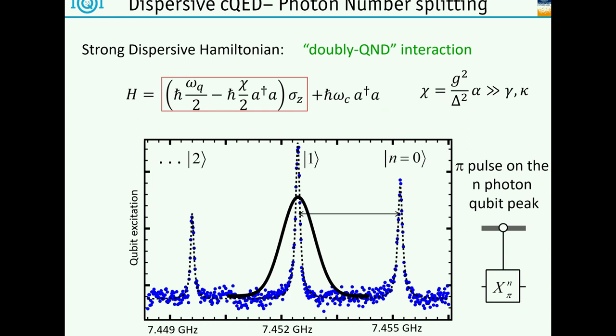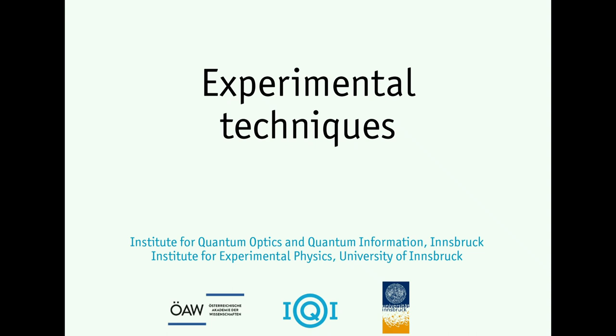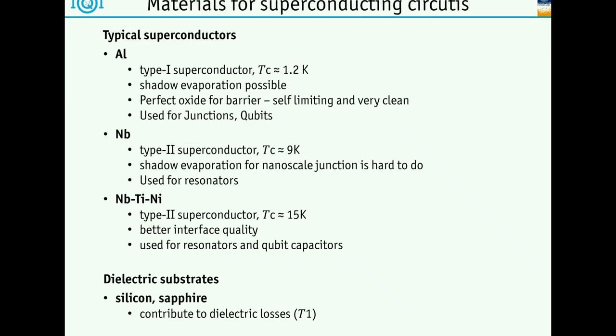What I actually wanted to talk a little bit about is some experimental techniques. What do we use in the lab to really control these types of superconducting circuits? Let's start out first: what are the types of superconductors we actually use? Typically, I would say in the community, we use these three. We use aluminum whenever we want to make junctions. Aluminum is a type 1 superconductor with a transition temperature of about a Kelvin. Aluminum has the advantage that if I oxidize it, it forms a perfect insulator, very close to sapphire. I mean, it's amorphous aluminum oxide, but it forms a perfect barrier for a Josephson junction.